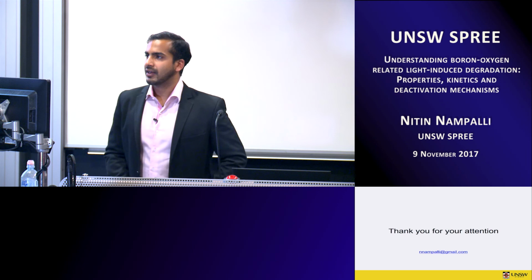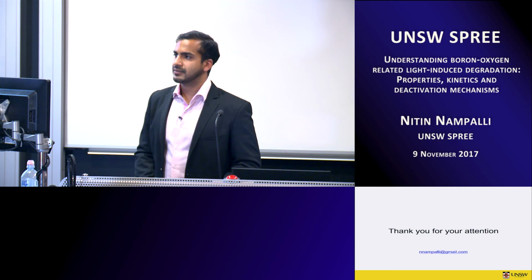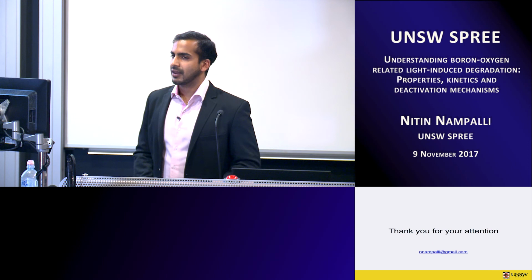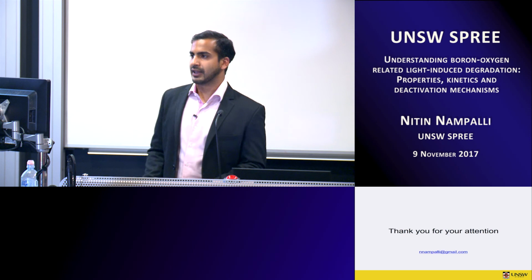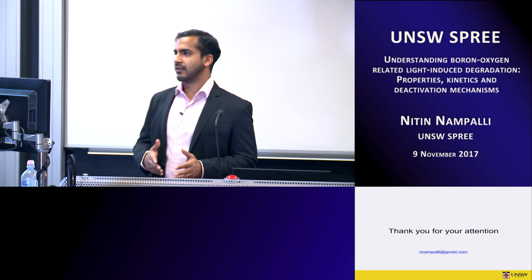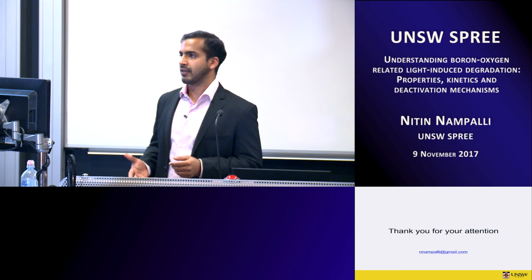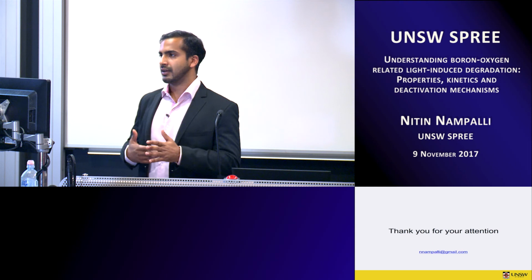Alison? It was a really nice talk, thank you. With the firing experiments and the high temperature, I thought you said it was not boron-oxygen. Is there a reason why you thought it was not boron-oxygen, the defect that's activated at the high temperatures? So, if you look at the capture cross-section ratio that was fitted, at lower temperatures it's pretty clear that it is boron-oxygen because the capture cross-section doesn't change, and then suddenly at this high temperature, about 650, the fitted capture cross-section ratio started changing quite a bit.